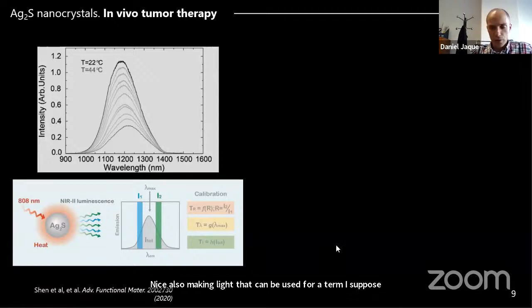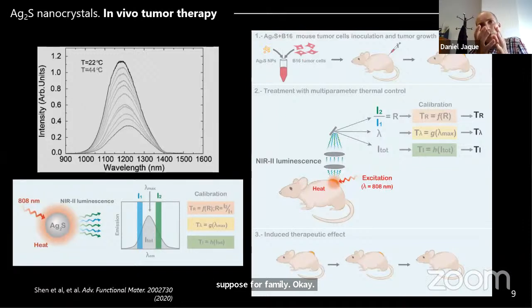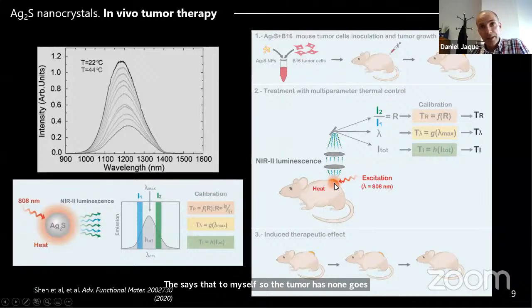So in principle we can use these nanoparticles to treat a tumor, because we inject the nanoparticles into the tumor and then we heat the tumor and we kill the tumor. At the same time, we are collecting the luminescence and we are calculating the temperature of the tumor. That's important because we want to control the temperature at which we are heating the tumor, because we don't want to create damage in the surrounding tissues. So this was the idea. We inject the nanoparticles, so the tumor cells have nanoparticles inside. We excite them, creating heat, and then the luminescence from the tumor can be analyzed and can give us different thermal readings.